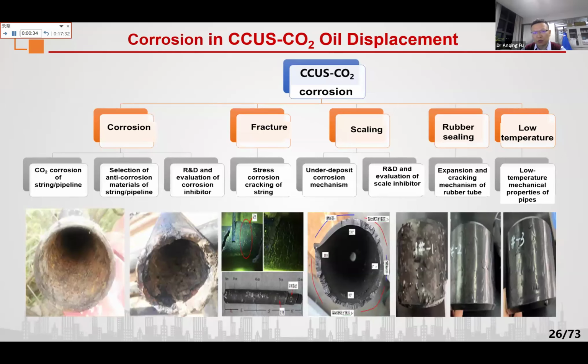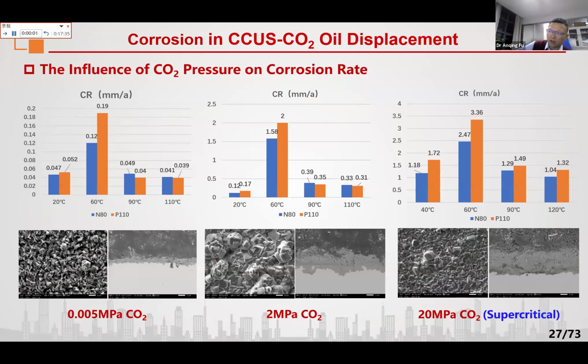In the following slides, I will show you the research results from our lab. The first one is the influence of CO2 pressure on the corrosion rate. The corrosion rate is substantially increased when the CO2 reaches the supercritical state. You can see from these 3 diagrams, when the CO2 reached 20 megapascal, which is a supercritical state, the corrosion rate, no matter for N80 or P110, these two kinds of low carbon steel tubing, increased in the supercritical state.